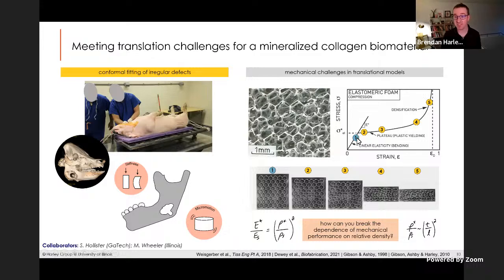But in a porous material, it's added because you have all these pores. So what you see is what's known as a linear elastic regime. That's a regime where the pores are starting to deform. The fibers that define the pores start to bend. And so you can see it graphically here on the bottom using honeycomb materials we made out of rubber. Initially you load it and everything deflects a little bit. You reach a point known as the collapse plateau, which is where all of a sudden the fibers that make up the pores start buckling and the pore collapses on itself.